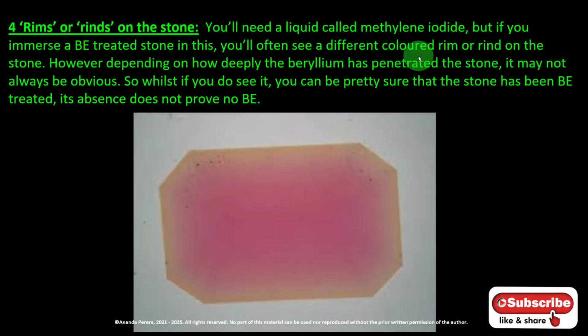You will often see a different colored rim. See the rim, orange color rim around the stone, and the center is another color. It may not always be obvious. So if you do see it, you can be pretty sure that the stone has been beryllium treated. Its absence does not prove no beryllium. In this area, no beryllium. But around the rim, there's beryllium. So this is a very good thing. We need methylene iodide liquid to immerse the stone.